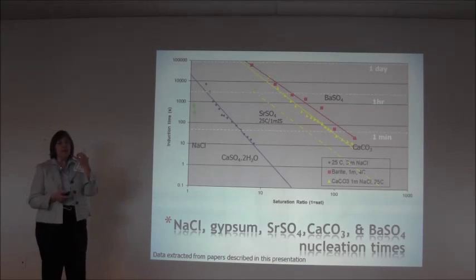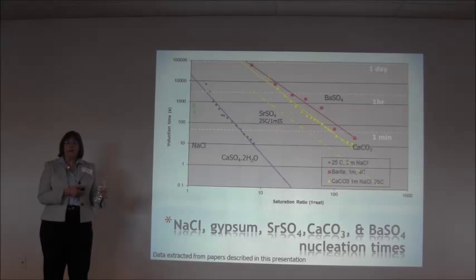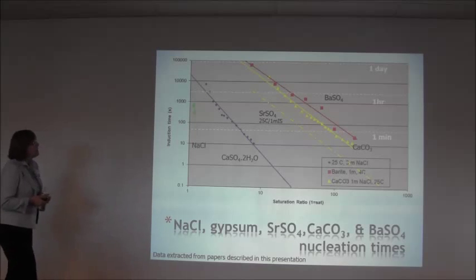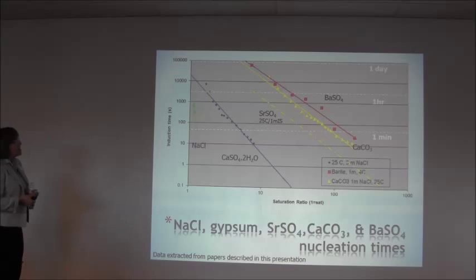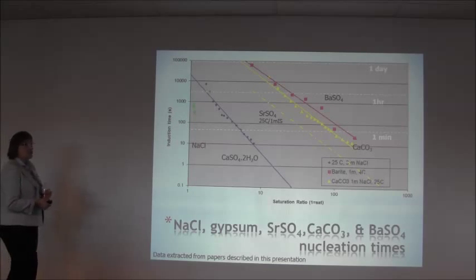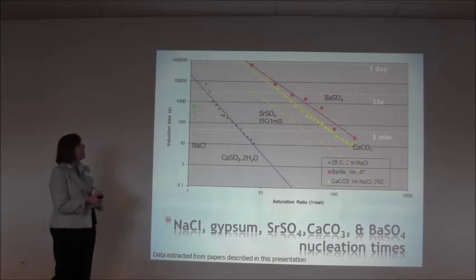So one of the things that we do as consultants, because remember I said that AQSIM has started to sell OLI software, we also consult with OLI software, so we're applications people. We take information like this, and we've created this particular slide for our own reference, and what it's doing is for the oil field scales that we are most interested in, the halite, the gypsum, the calcite, the barite, we've just developed timetables for kinetics. This is a log-log plot. It's saturation ratio versus the time, and the symbols are the scale tendencies, the saturation tendency ratio.